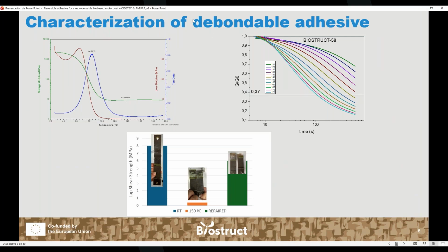And in order to demonstrate and to characterize these dynamic and reversible properties, we performed stress relaxation tests at different temperatures. For that, we heat the material at different temperatures and we apply a strain of around 1%. And we monitor how the relaxation modulus decreases over time. As the temperature increases, this relaxation is faster, allowing an easier debonding. So this demonstrates that this material is dynamic.